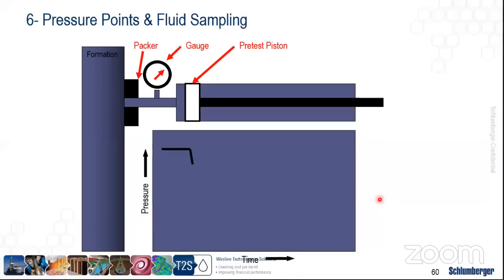So for pressure to be measured, we need to create a negative pressure inside the tool. We need to make a delta P. This negative pressure is typically happening due to the vacuum that we create inside the tool. So what typically happens is that we go to the formation that we need to test or measure the pressure for. We put the tool in stationary mode, and then we insert what we call a packer. This packer comes into contact with the formation. So this is the formation and this is the borehole itself. And this probe now is completely in contact with the formation, which makes a complete seal. And the only communication now will be coming from the formation itself all the way inside the tool through this flow line.